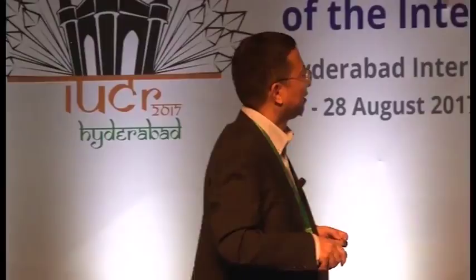This is due to when we added the cation A2, we can tune the distortion of the framework and reduce the distortion. So we can tune the ferroelectric ordering temperature, since actually the ferroelectric properties are mainly due to the framework and also the guest molecules. At the same time, these compounds also show magnetic ordering due to spin canting.